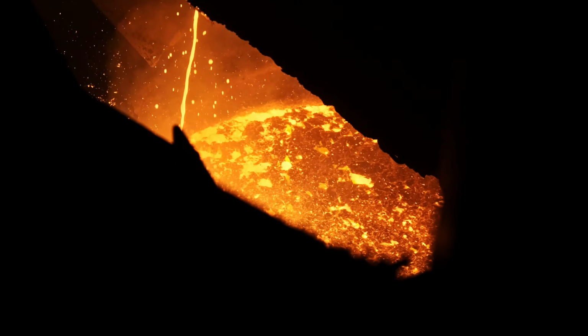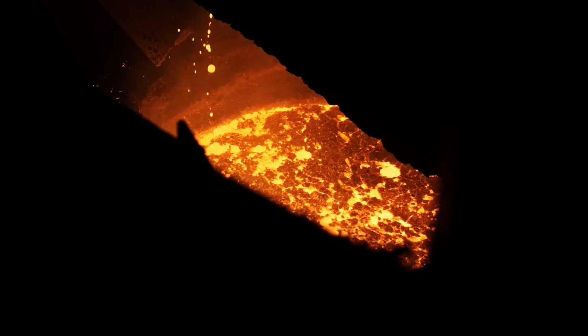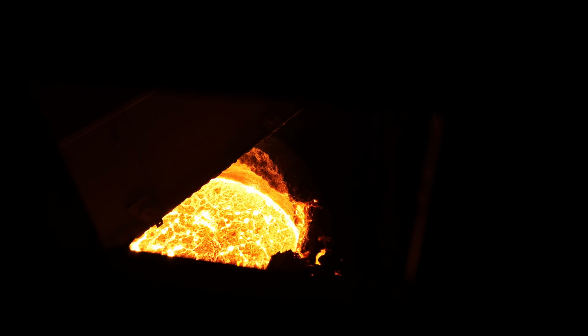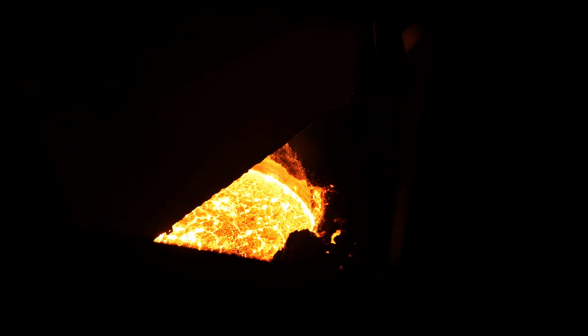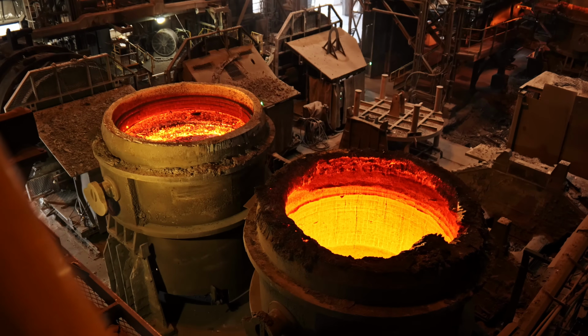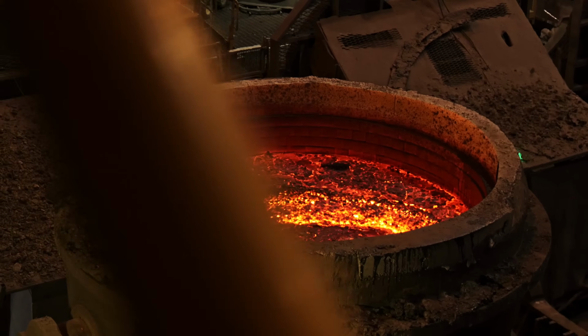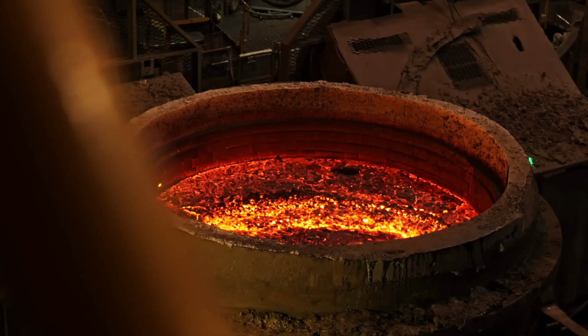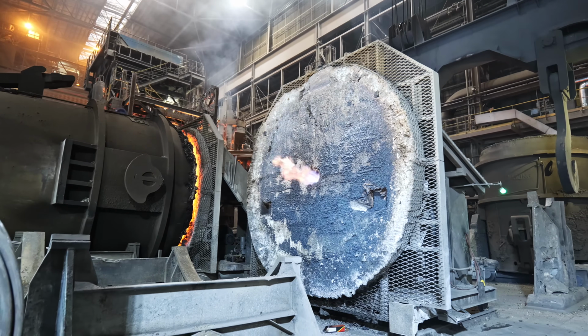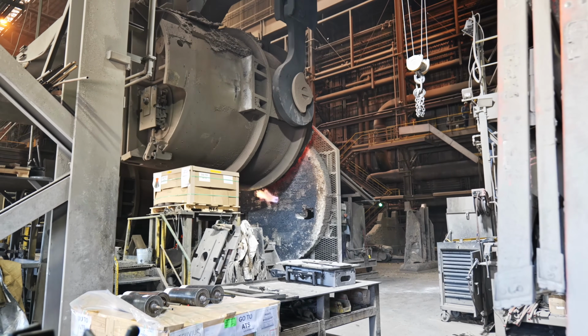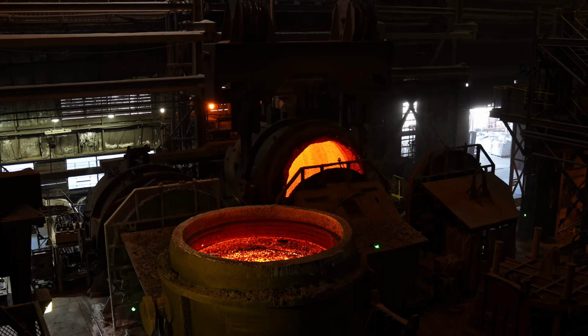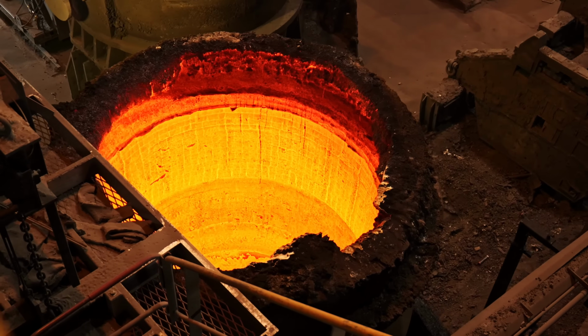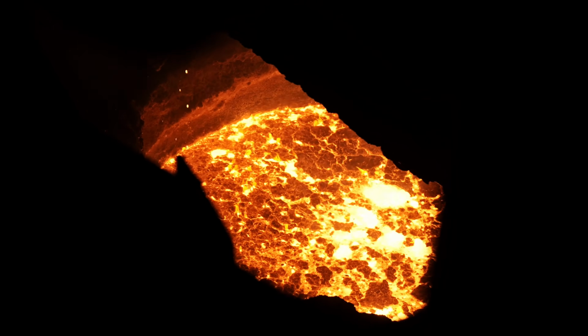A lot of that is concealed and contained, where it's a bottom tapping furnace, eccentric bottom tapping, so it'll drain vertically into a ladle, which you called the cauldron there, which is a good description. And the ladle is just a big metal vessel lined with a refractory brick. It's mostly a magnesium oxide brick with a real high melting point. And so we'll start with a warm ladle so that we don't shock it, and we add hot steel to that. So when we tap the furnace and it's around 2,900 degrees Fahrenheit, that'll fill a ladle full of steel. And for us, that heat size will be about 150 to 155 liquid tons of steel.